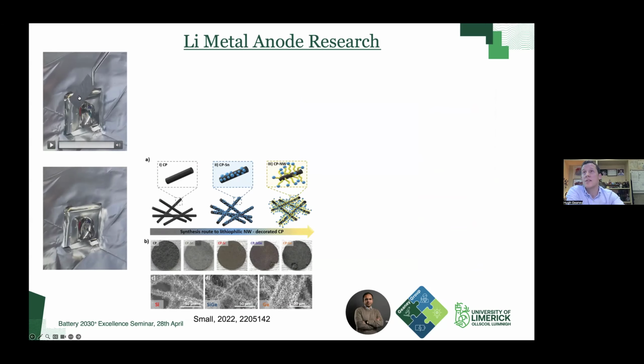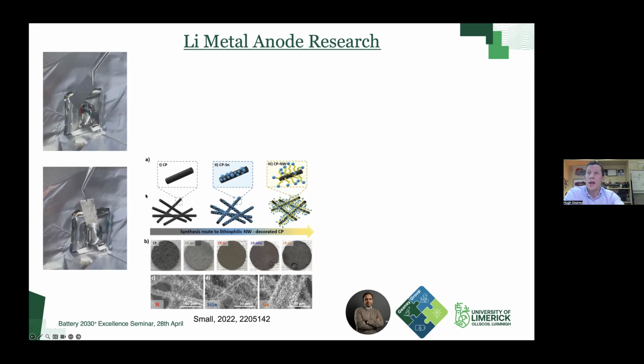What you can see is that this is a super lithophobic surface up here. So when you try and incorporate that lithium metal into the carbon paper, it just does not infill. We had all of these established synthesis routes to grow these nanowires onto various surfaces. So we took the carbon paper, we deposited tin onto the surface, and then we grew various nanowire compositions on top. So we had silicon nanowires, we had silicon germanium, and then we had germanium at the end. And as soon as you try and incorporate molten lithium onto those, these are super lithophilic substrates. So what happened is that it immediately infilled.